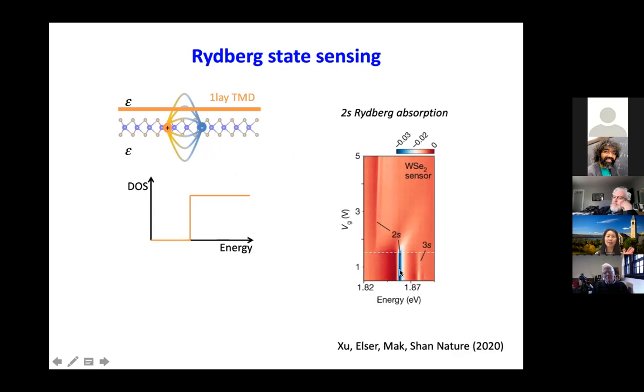And this is the 2s state, the 3s state, and 1s is at lower energy, and the intensity is very high. I'm skipping it, okay? So this dashed line divides this: below it, the sample is charge neutral, and above it, this sample is n-doped with electrons. And then you can see that this 2s state suddenly loses its spectral weight. And also there's a red shift. And this is all consistent with what we understand about the excitons in a single sheet of material.